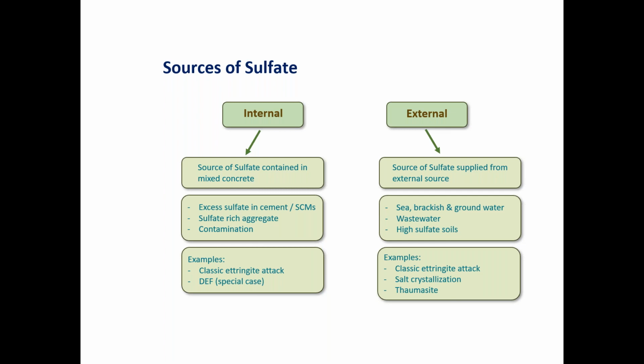So you have things like seawater, groundwater, wastewater. I remember very early in my career realizing that there's something unique about wastewater treatment plants, because when I looked at specifications and tried to design mixes to meet them, I always had these really interesting requirements. They always seemed to be excessive, very low water-cement ratios that produce very high strength concrete, with strengths that they're only needing, 3,500 or 4,000 psi, maybe 4,500.